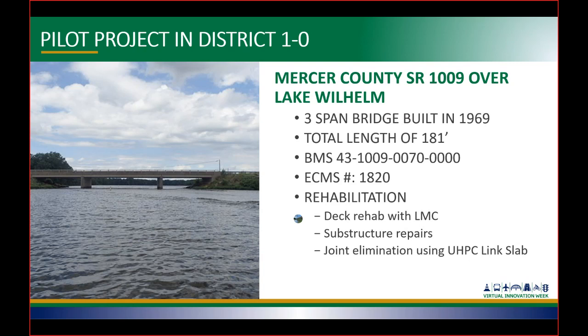We had planned on doing a scarification to the existing bridge deck and then applying a latex modified concrete overlay. We had to do some minor substructure repairs, but primarily the main thing we were trying to accomplish here was to implement the UHPC and eliminate the joints that were located over the piers.